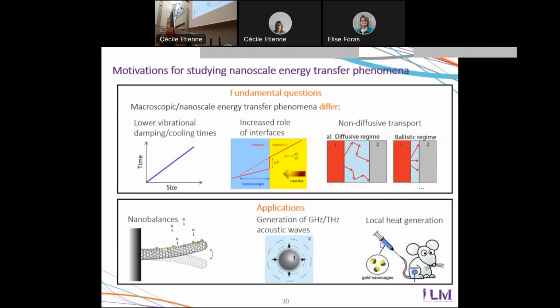What are our motivations for studying energy transfer at the nanoscale, on which I will concentrate in the next two parts of the talk? The key idea here is that at the nanoscale, there are strong differences between the modalities of energy transfer and those at macroscopic scales. Three of them are listed here. The first main difference is that the characteristic times, or at least some of them, associated to energy transfer processes are much faster. The characteristic time, in some cases, scales as the size. So as you reduce size, you go to shorter and shorter characteristic times.